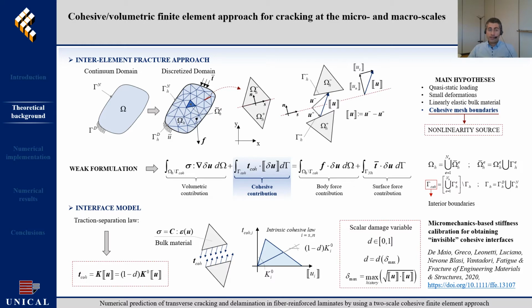In the present multiscale approach, multiple cracking at both the microscopic and macroscopic scales is accounted for by adopting a cohesive volumetric finite element approach. The underlying variational formulation assumes the constitutive behavior of embedded interfaces as the unique source of nonlinearity. It is worth highlighting the presence of an additional contribution in the resulting weak form, which represents the virtual work of the traction transferred by the embedded interfaces.